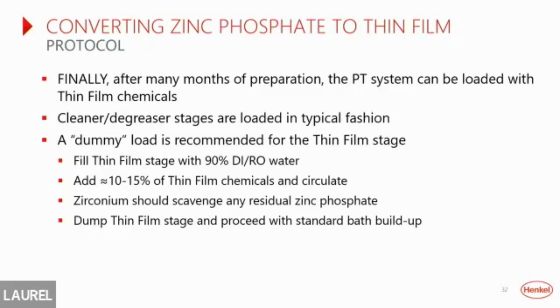It may be a different cleaner with zirconium than with zinc phosphate. But as far as the first time you fill the zirconium stage after a clean out or conversion, we recommend a dummy charge. What that is, you're going to fill it up with water and add a small amount of the zirconium material to make it up, okay?